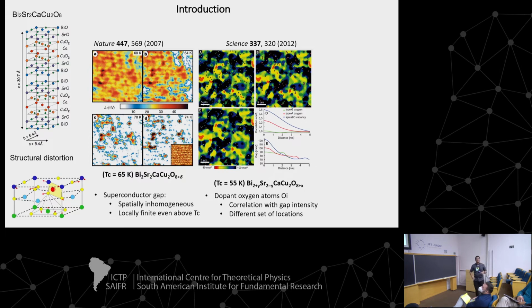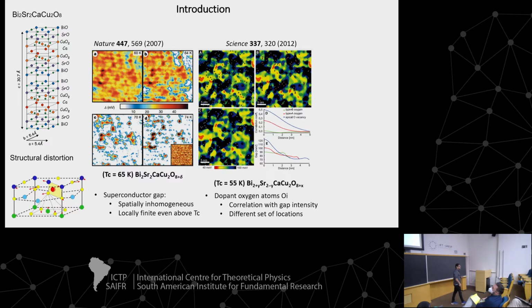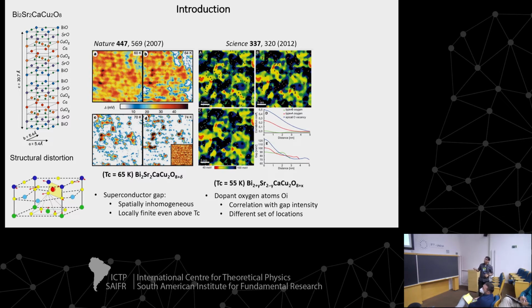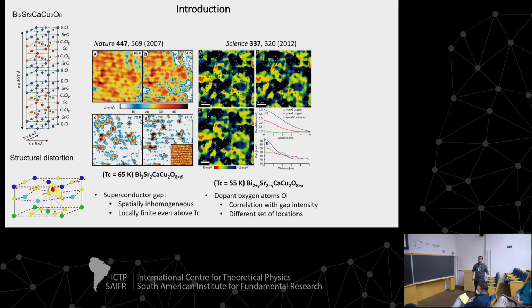Again, recently we have seen that the electron-phonon interaction is even more important in cuprates than we thought. For instance, this is one example of a class of cuprates that when you start doping with oxygens, we see, from I believe this is STM, the formation of the gap. And the formation of the gap is completely inhomogeneous. And when we look where the oxygens are, actually, the important one is this one here, the interstitial oxygens. So we see that the oxygens are exactly at the same regions where we have the gap formation. And these interstitial oxygens do not lead to doping. They basically lead to a structural distortion. So obviously here we have some kind of effect coming from the electron-phonon interaction.